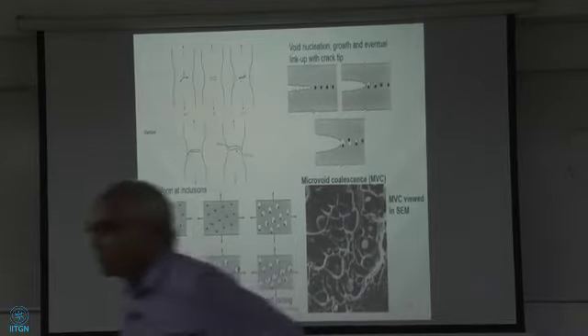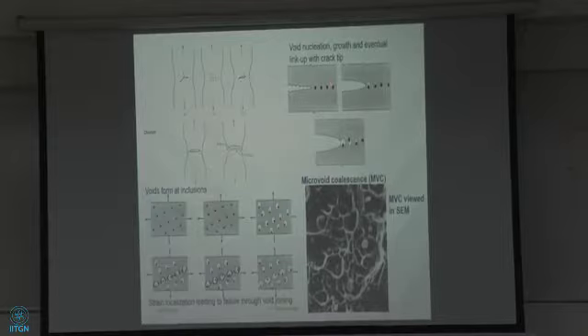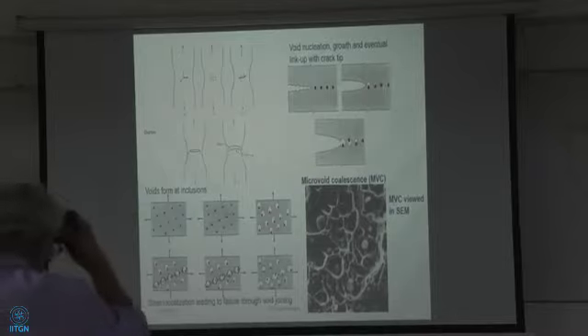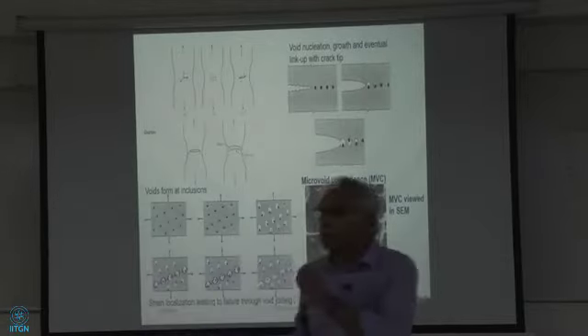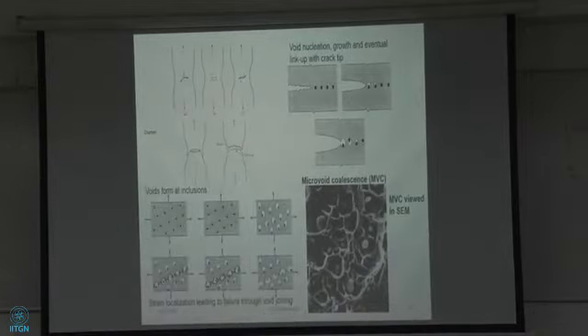Due to that void, the edge is blunt, no? How can the crack tip grow? When the edge is sharp, stress will be high. Then only the crack grows faster. Right, so you're talking about fatigue. Yes. This is static. This is like a fracture toughness. You're right about that. When it comes to fatigue, it cannot grow if it becomes blunt. It has to remain sharp. But this is an example. So what I did here is, this is a uniaxial tension. This is like a fracture toughness sample with a crack in it. As you're pulling it, that's what is happening. Okay? But you're right. When it comes to fatigue, you're absolutely correct.